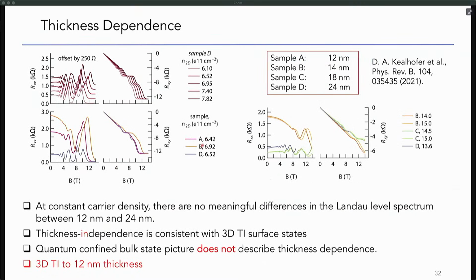But rather, if you look at films in the thickness range between 12 and 24 nanometers, and tune the carrier densities to be identical between these films, you can see the Shubnikov-de Haas oscillations look rather identical despite us having varied the thicknesses. So this confirms what I just told you about the interpretation of the quantum Hall effect. We have 3D TI surface states in these films, which explains the thickness independence and the sequences in the quantum Hall effect. And it also means that for fairly thin film thicknesses, down to 12 nanometers, we still have this 3D TI state.